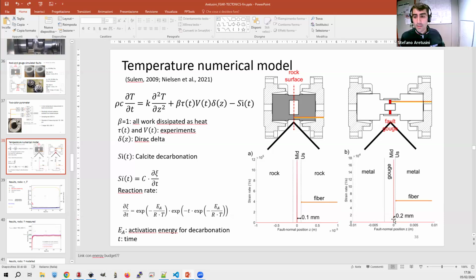And it's true, even if the maximum localization was set on the opposite side, between the rock and the gouge layer, the temperature measured by the fiber would be almost blind, because temperatures are still measurable above 400 C. By the time the temperature is diffusing across the gouge layer, we had a low temperature anomaly, and the shape was more smooth compared to the actual measurement we have.